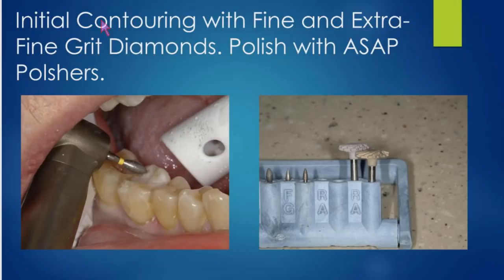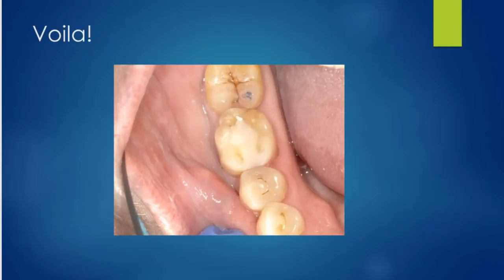Because it's sculptable, there's not a lot of excess flash that we have to remove, so I'll come in with an extra fine OS1 burr and smooth that off, and then I will follow that up with these ASAP polishers that you see here from Clinician's Choice. I'm a big fan of those. If you want to go even simpler, you could use something like a brownie point, maybe at 10,000, 15,000 RPM with lots of water. That'll also give you a nice finish, though not quite as nice as these ASAP polishers from Clinician's Choice. So there's the final restoration.